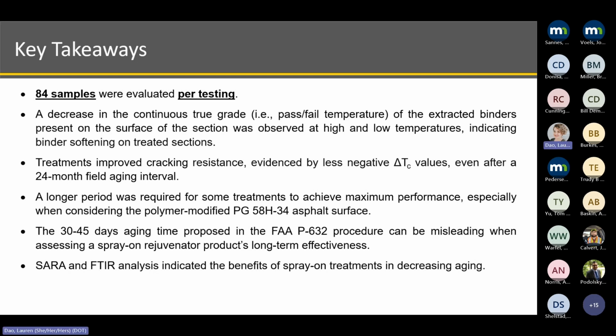From the data collected in this study so far, we see a decrease in the continuous true grade of the extracted binders at high temperatures and low, indicating the softening of the treated sections. We see also that these treatments improve the cracking resistance as indicated by the delta TC, even after 24 months of being applied. A longer period was required for some treatments to achieve a maximum performance, especially when considering the surface containing the polymeric asphalt binder. So therefore, the window of 30 to 45 days after the treatments being applied can be misleading. And the chemical analysis performed so far has indicated the benefits of these treatments.